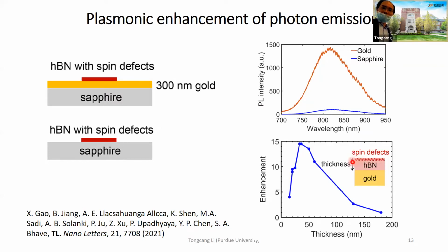Only the top few nanometers have spin defects, and then we can control the thickness. That means we control the separation from the spin defect to the gold surface. By changing the separation, we can see the enhancement reaches a peak when the thickness is about 40 nanometers, and then decreases very fast for thicker flakes. That shows this is really due to plasmonic enhancement instead of just reflection.